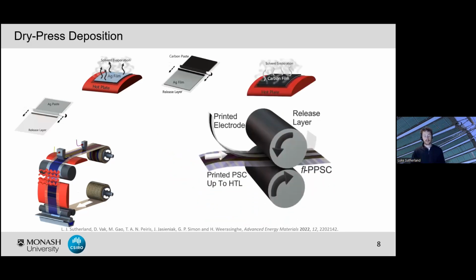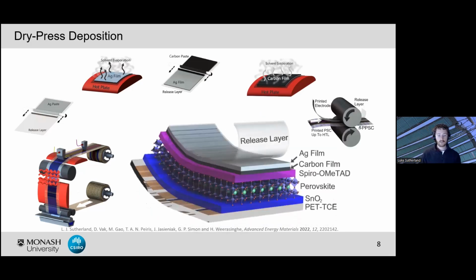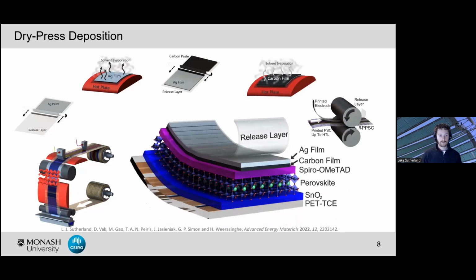We then bring the two together, so our perovskite solar cell up to the HTL and our coated electrode on our release layer substrate, and we simply transfer the electrode. So we're depositing the electrode using compression. So this is done in this case using a calender press, as we can see on screen here. Following the transfer, we simply peel off the release layer on the other side, exposing our silver film for electrical connection and finalizing the fabrication of our device.